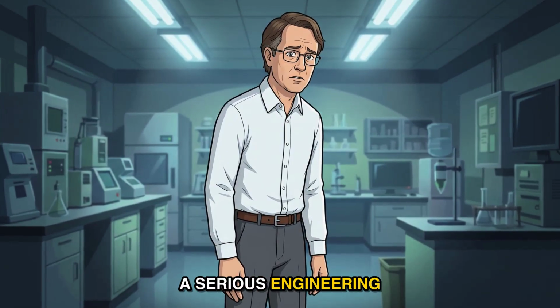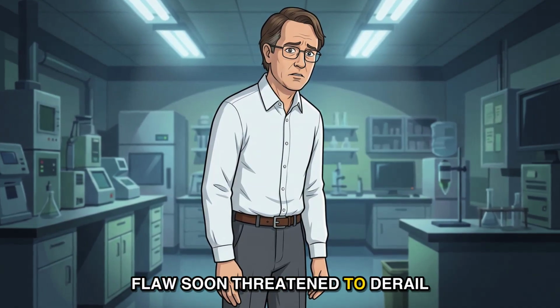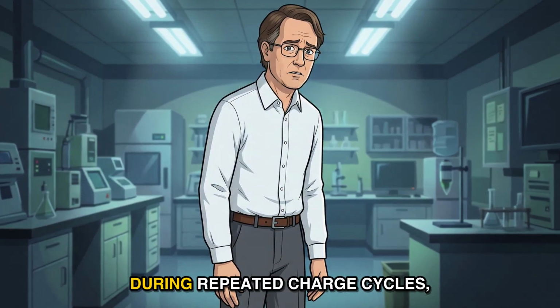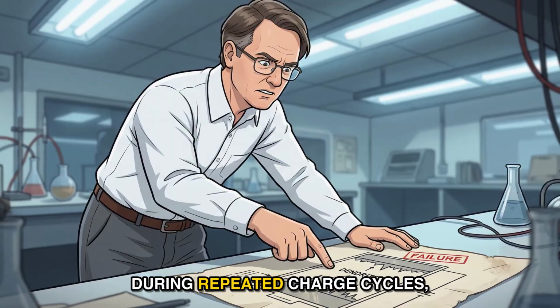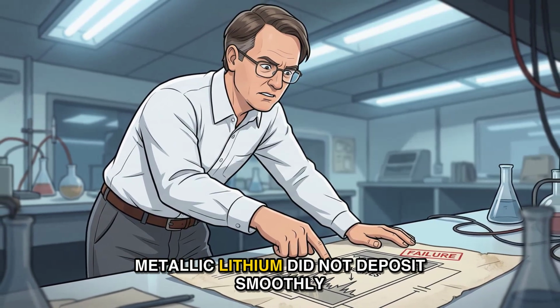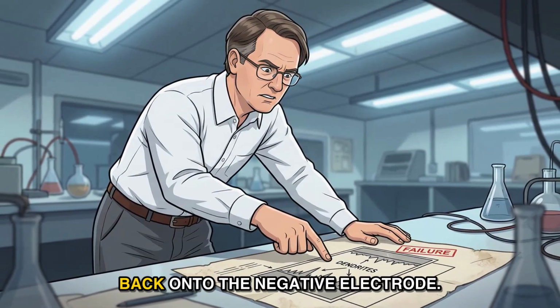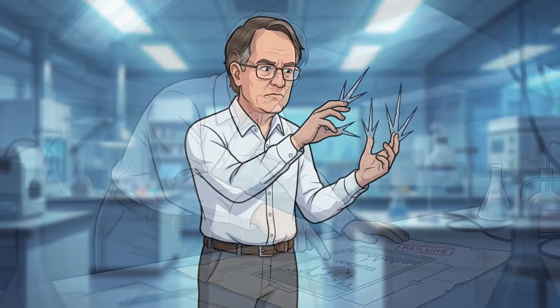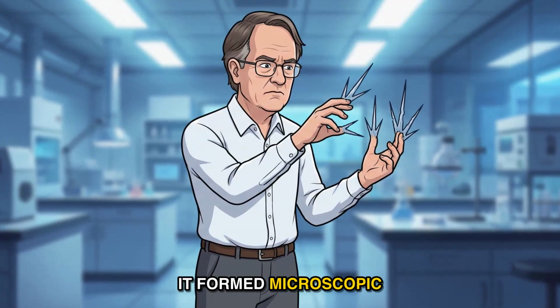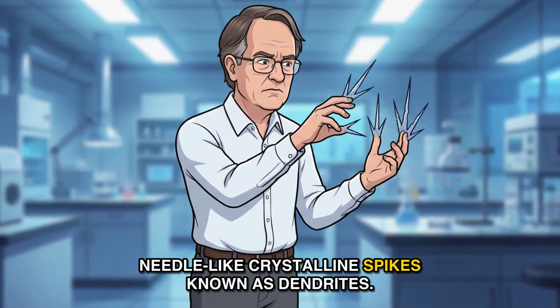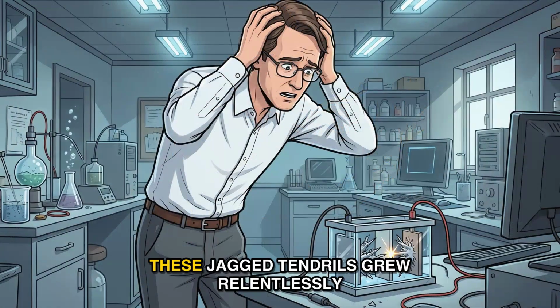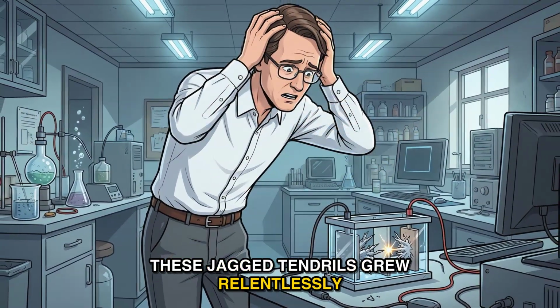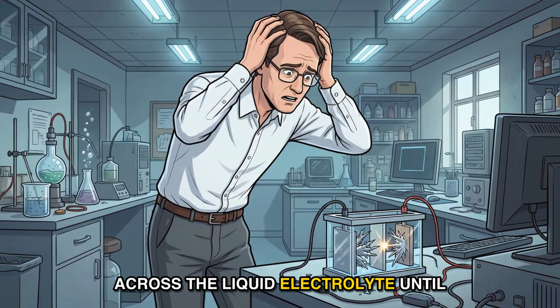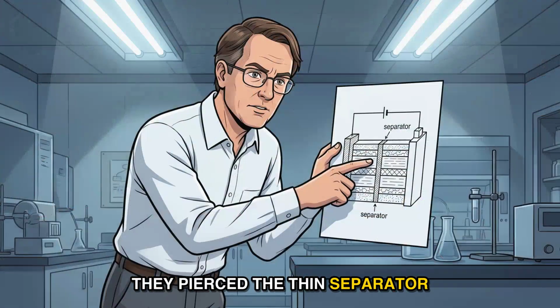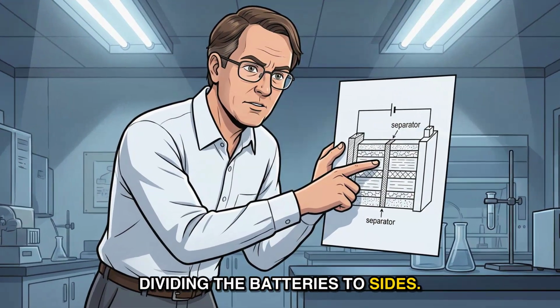However, a serious engineering flaw soon threatened to derail the entire innovation. During repeated charge cycles, metallic lithium did not deposit smoothly back onto the negative electrode. Instead, it formed microscopic needle-like crystalline spikes known as dendrites. These jagged tendrils grew relentlessly across the liquid electrolyte until they pierced the thin separator dividing the battery's two sides.